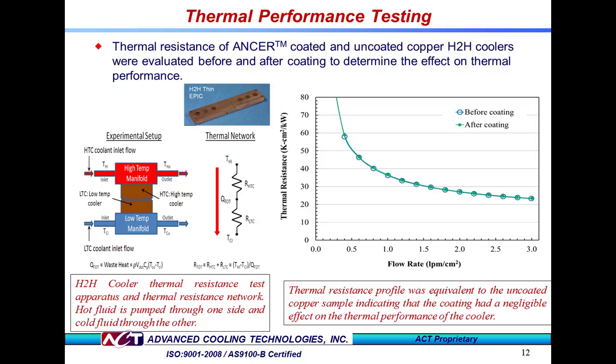Here we test if the ANCER coating affects the heat transfer performance of the MCCs. To do so, we utilize head-to-head, H2H, copper microchannel coolers from SRL. H2H is a single cooler with two coolers integrated head-to-head. One head is connected to a high-temperature coolant flow, which serves as a heat source, and the other head to a low-temperature coolant flow, which serves as a heat removal mechanism. Measurement of the delta T across the coolers enables the thermal resistance to be determined.